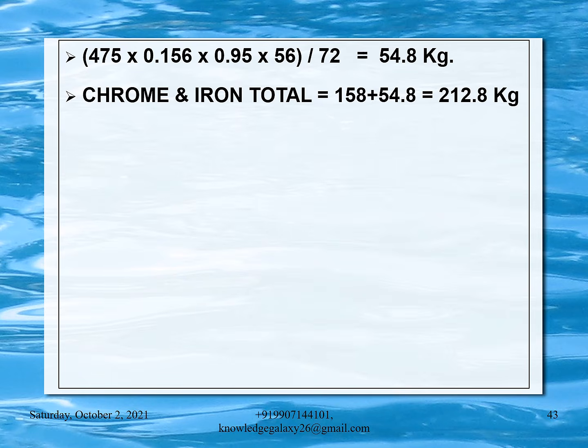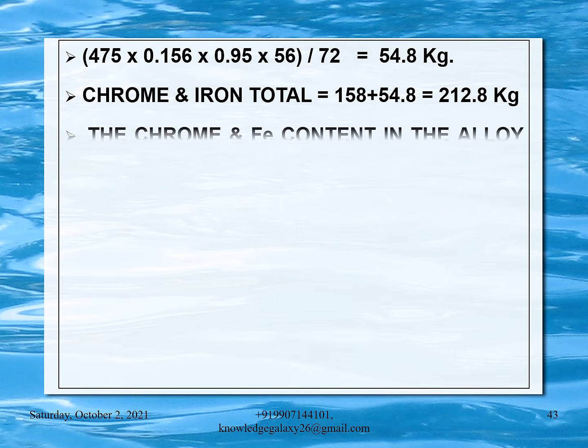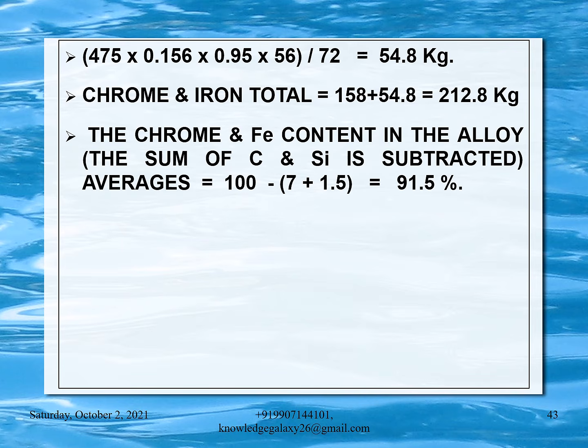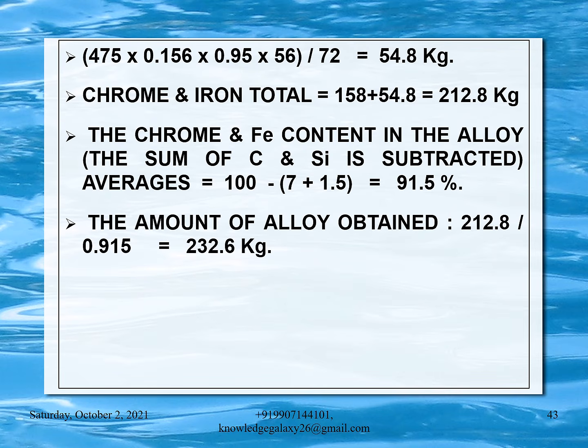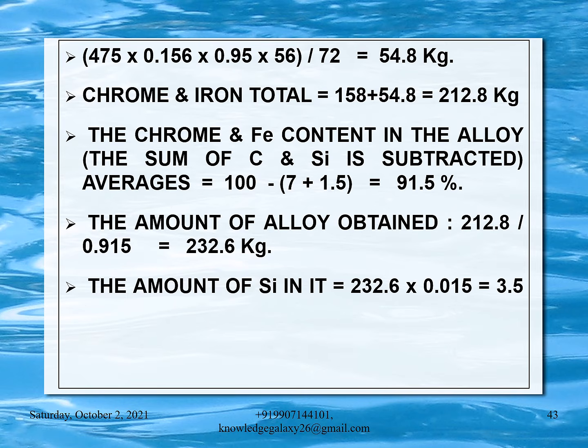Chrome and iron total is equal to 158 plus 54.8, which comes to 212.8 kg. The chrome and iron contained in the alloy, the sum of carbon and silicon is subtracted, averages 100 minus 7 plus 1.5 is equal to 91.5%. The amount of alloy obtained is equal to 212.8 divided by 0.915 is equal to 232.6 kg. The amount of silicon in it is 232.6 into 0.015 is equal to 3.5 kg. Here 0.015 is 1.5% silicon in the alloy.